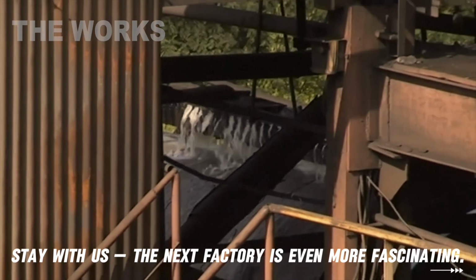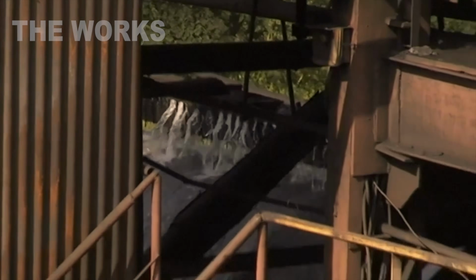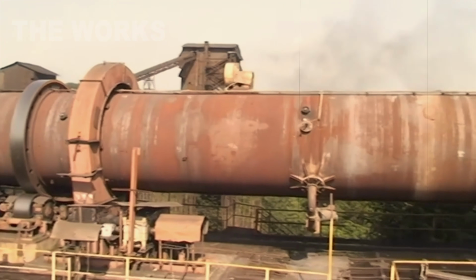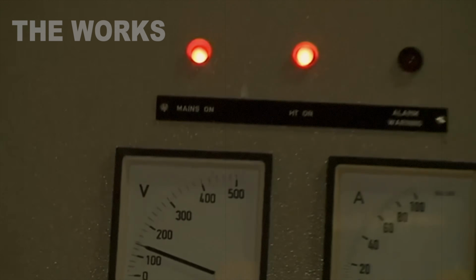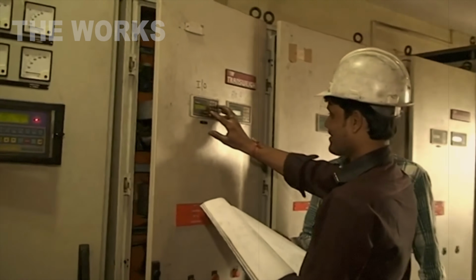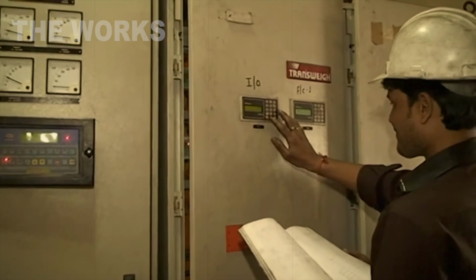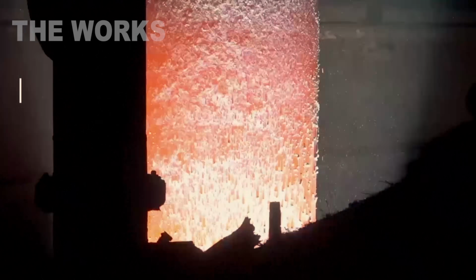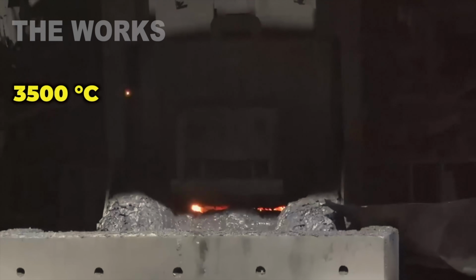The sponge iron gets loaded into an electric arc furnace, a massive steel vessel with graphite electrodes as thick as telephone poles. They run monstrous electrical current through these electrodes, tens of thousands of amps. Between the electrodes and the metal, an electric arc forms with temperatures reaching 6,300 degrees Fahrenheit. That's hotter than the surface of the sun. The iron melts in minutes.